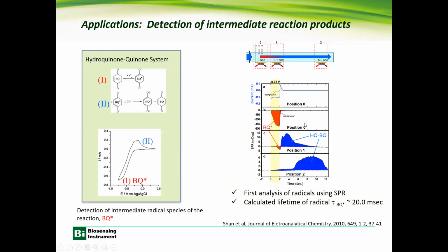And the result is shown here. First of all, at the potential 0, you generate the intermediate molecules, and by controlling the potential, you can measure the changes of the intermediate materials as a function of time. By analyzing this data, you can figure out, for example, the lifetime of this radical, which in this case is roughly about 20 milliseconds. So this is a powerful technique, a new application. Like I said, you can design based on these two techniques.